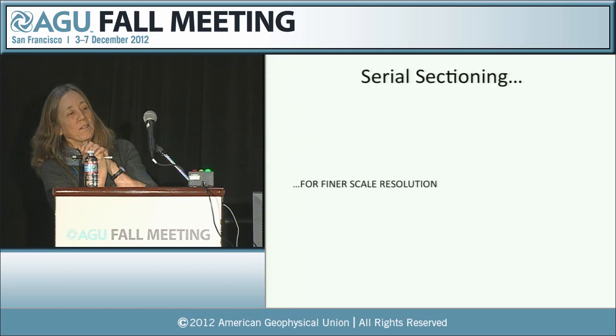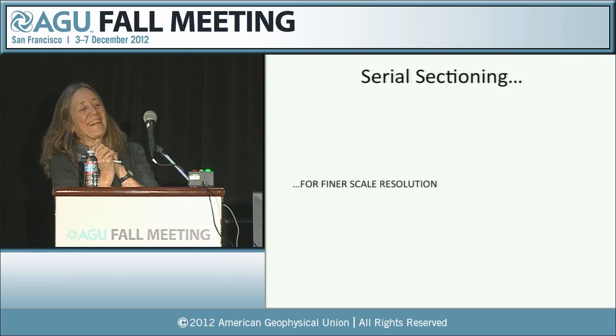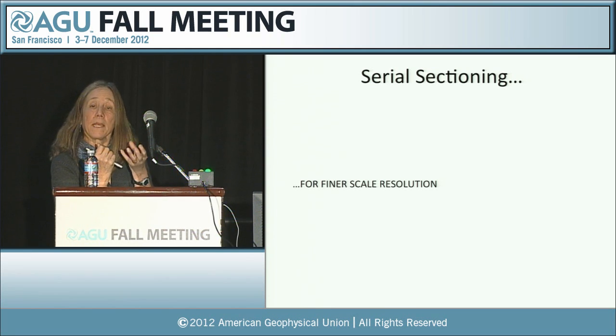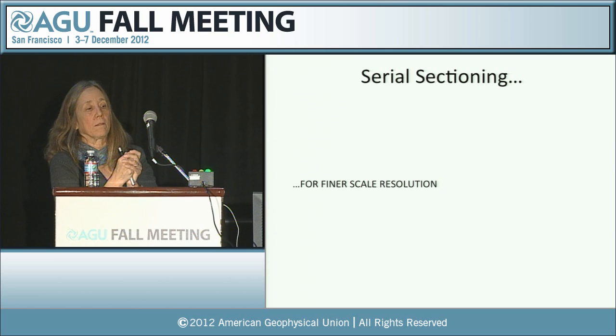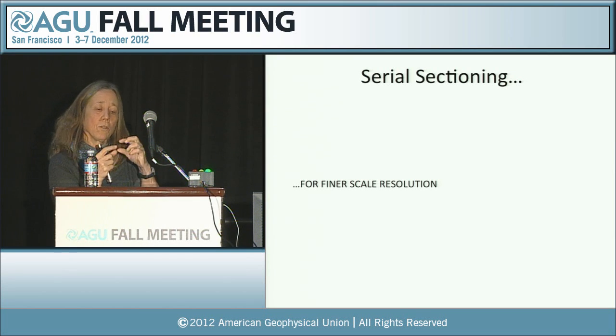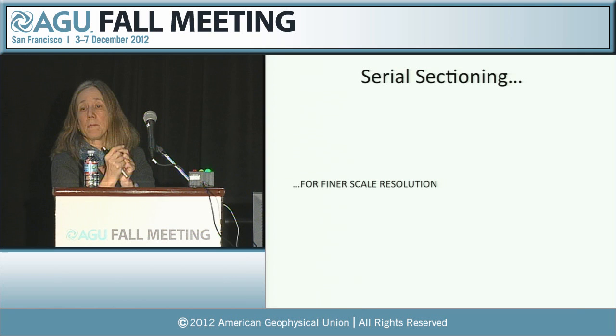And so my last few slides show you a mass balance that I did, trying to estimate for a given age, say a 105,000-year-old core, how big could that core be mixed with a zero-age rim to produce this 5,000-year maximum age that is seen in the single crystals. And it turns out that you could have a core that's as big as 70 microns across.